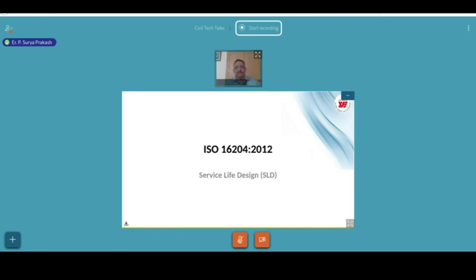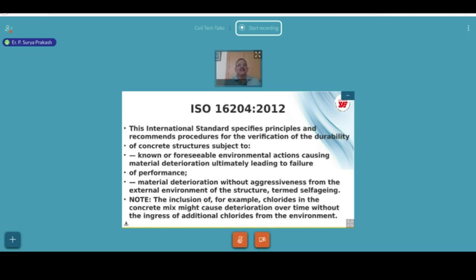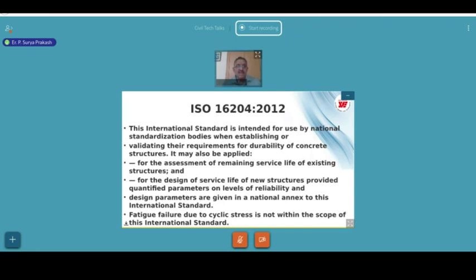So next is for service life design, the only document that we have readily available is ISO 16204, which is formulated in 2012, as late as 2012. Before that, there was no document. So you can do the service life design based on this, and it specifies principles and recommends procedures for verification of durability of concrete structure subject to known or foreseen environmental actions causing material deterioration, ultimately leading to failure of performance. And material deterioration without aggressiveness from the external environment of the structure is termed as self-aging. The inclusion of chlorides in the concrete mix might cause deterioration over time without the ingress of additional chlorides from the environment even.